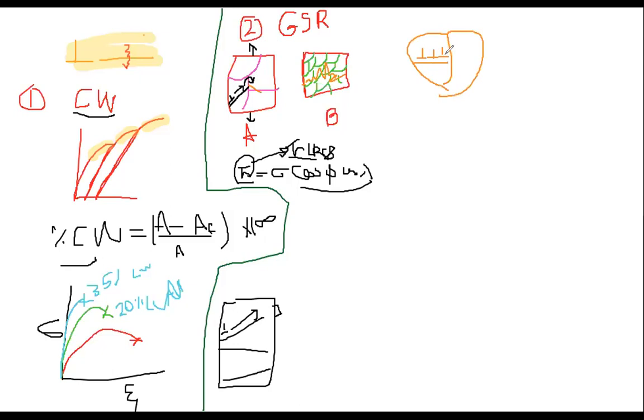So those dislocations are going to pile up on the boundary. They cannot go to the other grain because the other grain is still not active. There's not a single plane or single system of this plane that is active. That piling up will result in stress concentration that might multiply dislocations in neighboring grains.